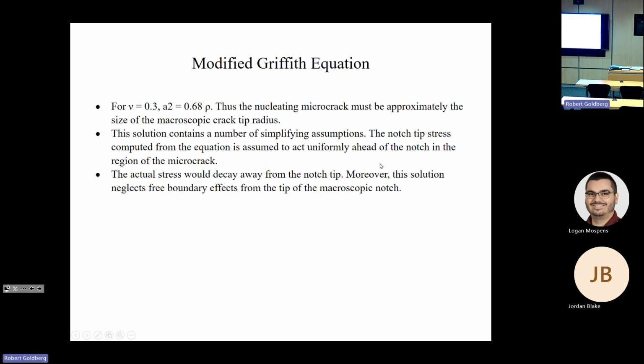So, couple of other points. For a Poisson ratio of 0.3, which is kind of a standard value of Poisson ratio, the half length of the micro crack is 0.68 rho, which would mean that the total crack length is about 1.4 times the radius of curvature. What this means is the nucleating microcrack is approximately the size of the crack tip radius.